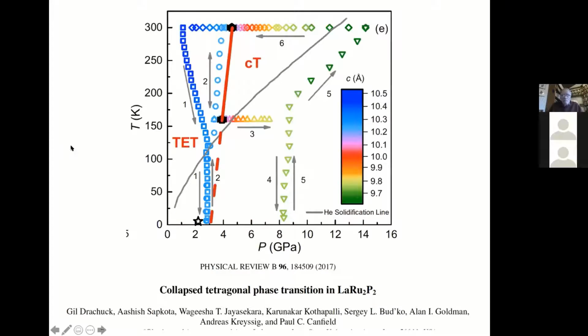Another material in this class that was studied under pressure was lanthanum ruthenium 2 phosphorus 2, and this is just a pressure temperature diagram. What you have out here with pressure has to do with which direction you're doing the experiment in. But there's a collapse from what they call tetragonal to the collapsed tetragonal. Same crystal structure. It's just you've gone from the long phosphorus bond length to the short.